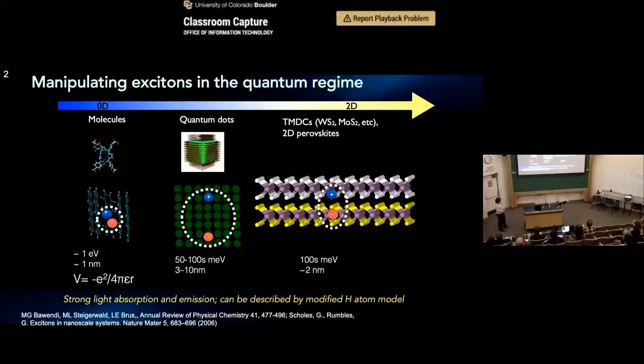How it works is that when you photoexcite an electron, say, from the valence band to the conduction band, you leave behind a hole in the valence band. Because of the Coulomb interaction between this positive hole and the negative charge electron, you can write down the potential energy for this quasi-particle, very similar to the Coulomb interaction between a proton and electron in a hydrogen atom. The only difference is that this Coulomb interaction is going to be normalized by the dielectric constant of your materials. And so if you solve the Schrodinger equation, you would get a wave function very reminiscent of these hydrogen atoms.